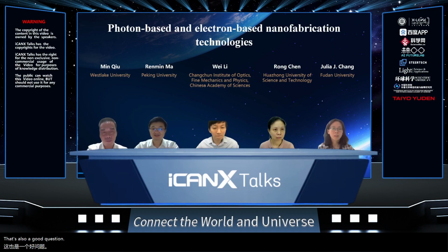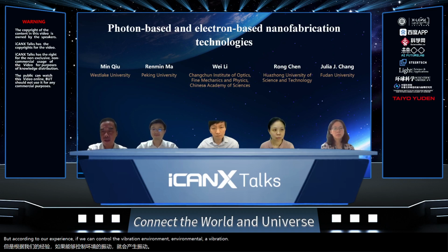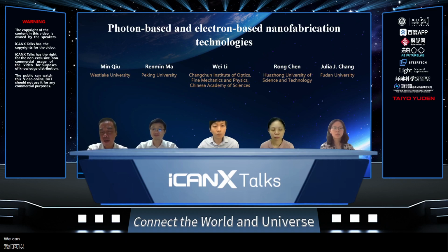That's also a good question. So the surface roughness first is very low, because as long as you control the temperature carefully, and when you move to the amorphous phase, the surface roughness is only a few nanometers, because it's roughly a very few layers of water molecules. While the edge roughness is a tricky issue. It depends on lots of things. But according to our experience, if we can control the environmental vibration properly, we can have very beautiful sidewall roughness. We can easily make a very high aspect ratio structure